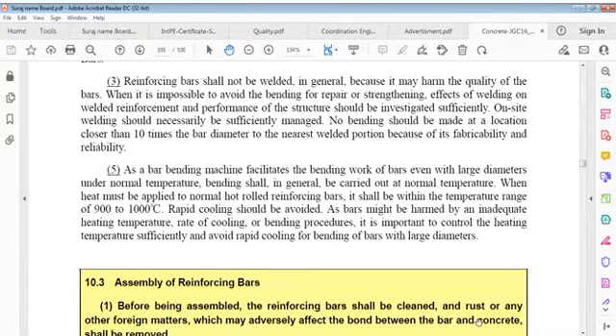When heat must be applied to normal hot rolled reinforcing bars, it shall be within a temperature range of 900 to 1000 degrees Celsius. Rapid cooling should be avoided. Bars might be harmed by an inadequate heating temperature, rate of cooling, or bending procedures. It is important to control heating temperature sufficiently and avoid rapid cooling for bending.